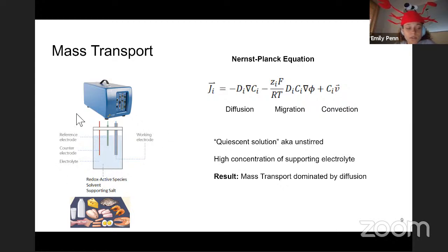Looking again at the three electrode system, which we described before, normally cyclic voltammetry is done in a quiescent solution, which is just a jargon word that means it's an unstirred, still solution. So this allows us to neglect the convection term in the Nernst-Planck equation. Also, you typically have a high concentration of supporting electrolyte. So this allows us to neglect the migration term. And as a result, we're just left with this first term, where our mass transport and the flux of the species i is dominated by this diffusion term, which comes from the concentration gradient in solution.